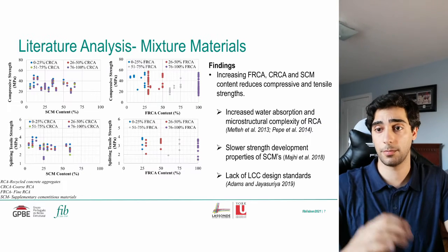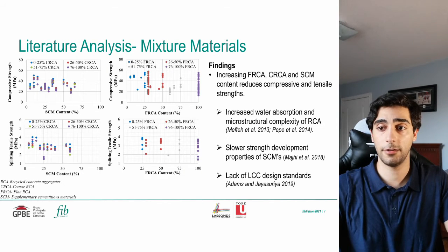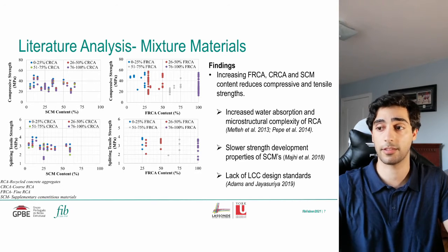In terms of the effect on the properties, we have four plots here. The top plots show the effect of coarse RCA and fine RCA content on the compressive strength values, while the bottom plots show their effect on the splitting tensile strength properties. The findings indicate that increasing fine, coarse RCA and SCM content reduces the compressive and tensile strengths.